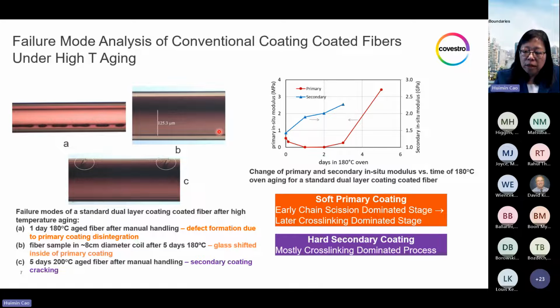Picture B is the same fiber wound into a small coil after 5 days of 180-degree aging. When this coil was unwound to be straight, the fiber was observed with the glass completely shifted to one side. The bottom side has no primary coating at all, and all the primary was squeezed to the upper side. This is the result of even very slight winding stress pushing the glass completely to one side, because the primary coating is no longer an elastic medium but behaves more like a liquid, so it can no longer hold the glass in place.